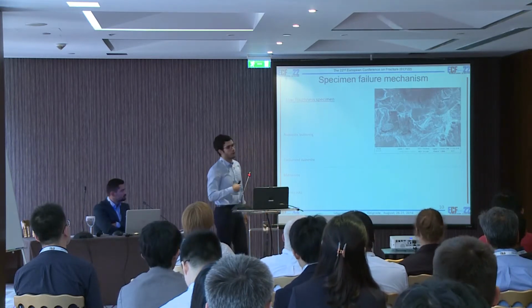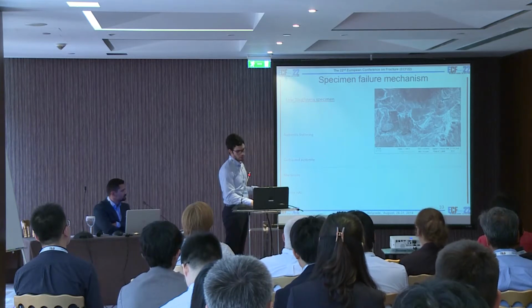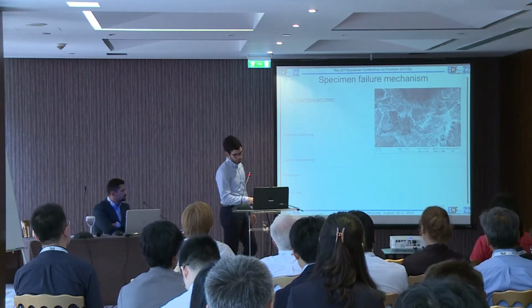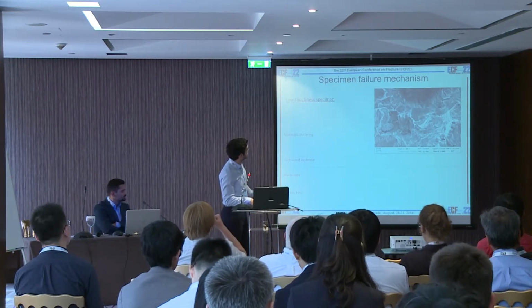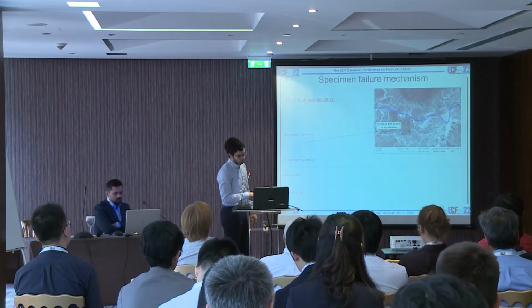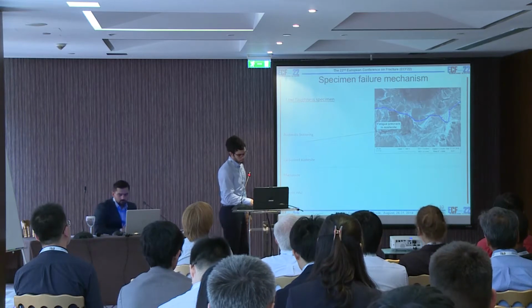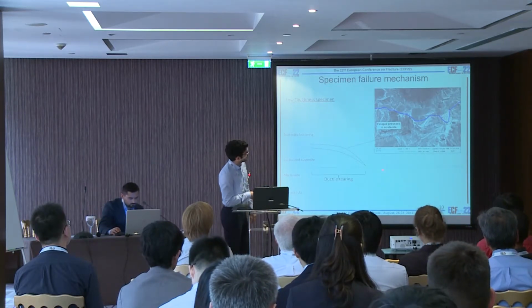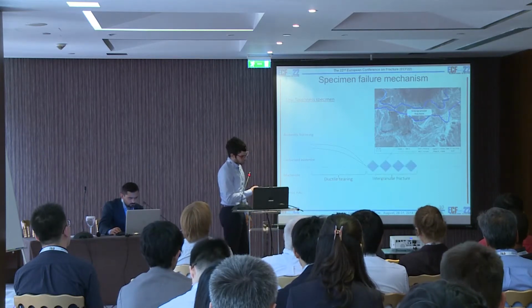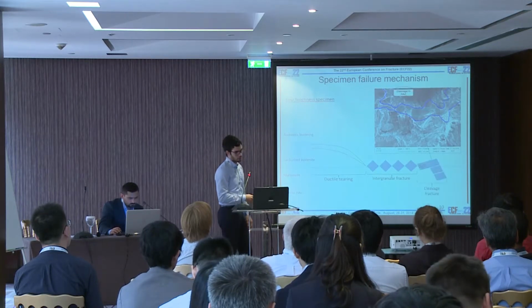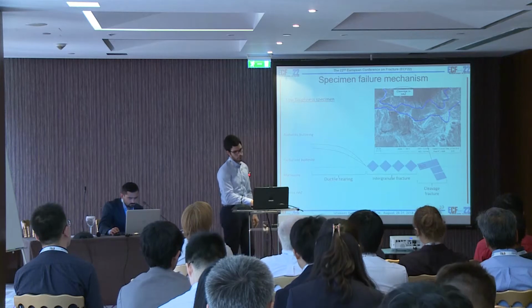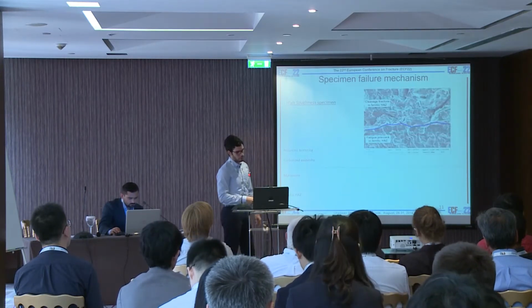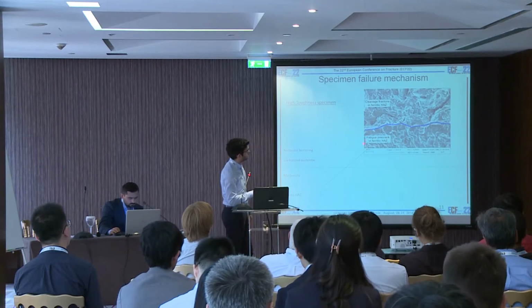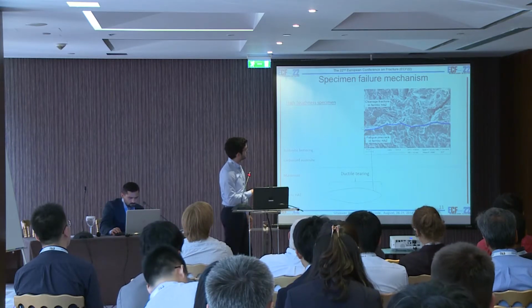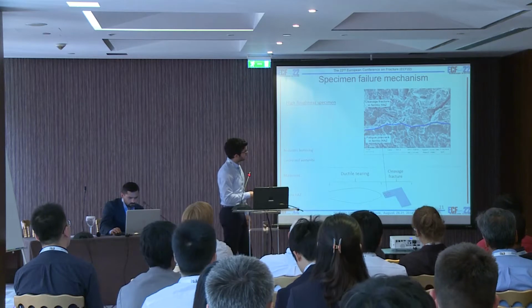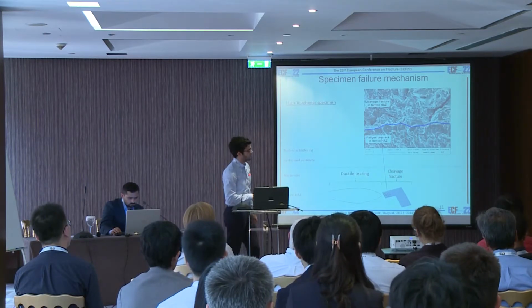So I don't have enough time to show you the higher toughness specimen, so I will just show you a schematic representation of the different failure mechanisms for the two configurations. So for the low toughness specimen configuration, we start from the fatigue pre-crack, which is in the austenite. Then we have crack deviation towards the MA interface with ductile tearing. Once we are there, we have intergranular fracture initiation, and then the crack deviates toward the ferritic side with cleavage fracture. For the high toughness specimen, on the other hand, we start from the fatigue pre-crack, which is in the ferritic side, and then we have some ductile tearing in the ferritic side, and the brittle fracture initiation is done with cleavage fracture.